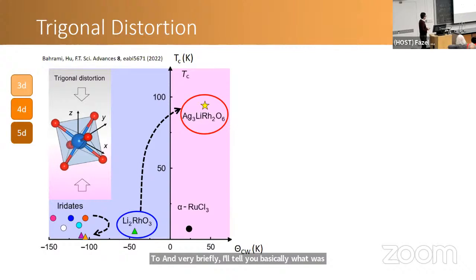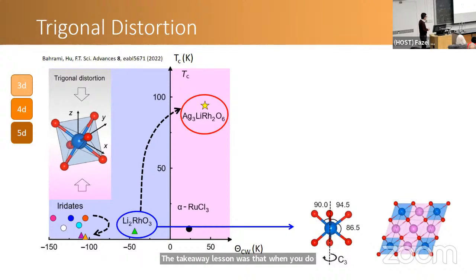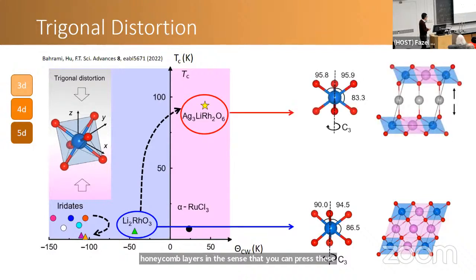The takeaway lesson was that when you do these exchange reactions, you actually change the structure of these rhodium octahedra within the honeycomb layers, in the sense that you compress these octahedra. This is called a trigonal compression, because the silver atoms are much less electropositive than the lithium atoms. They let go of these oxygens, and so the oxygens get closer to the rhodium atoms, and these rhodium-oxygen octahedra get squashed. This is called a trigonal compression.